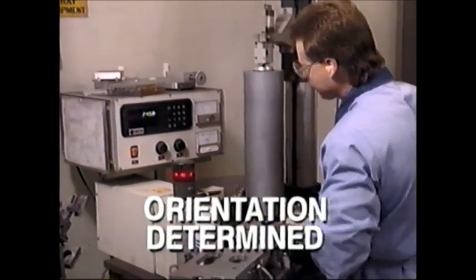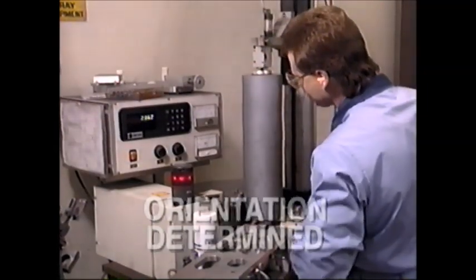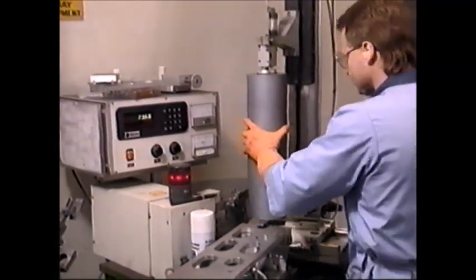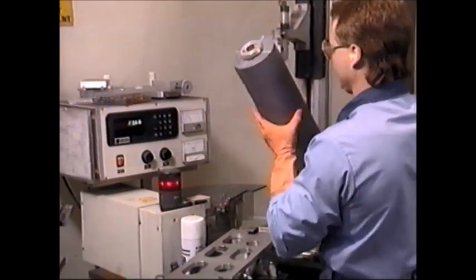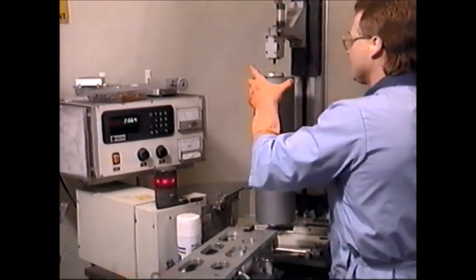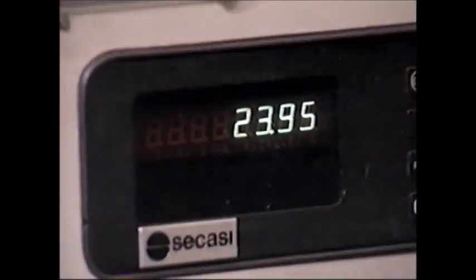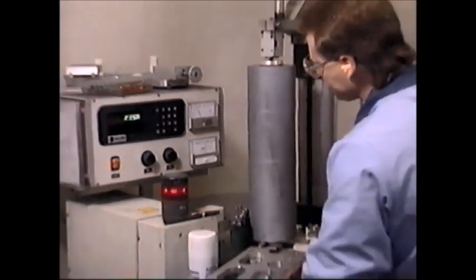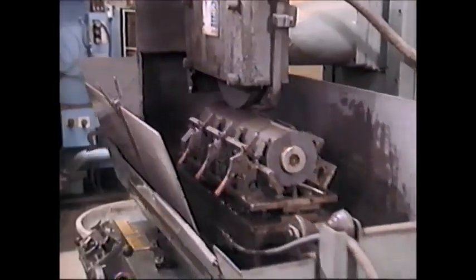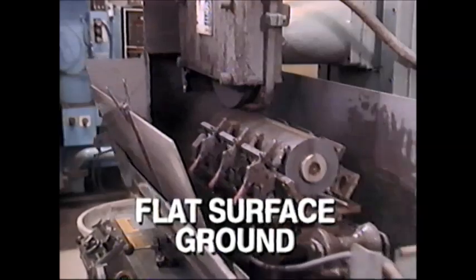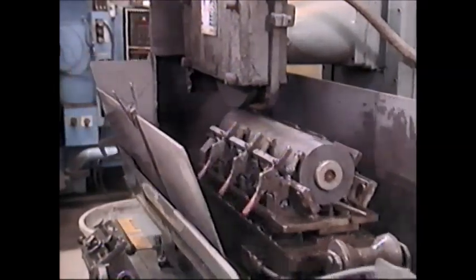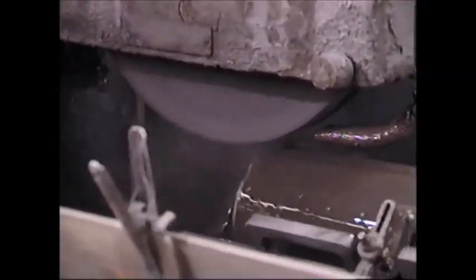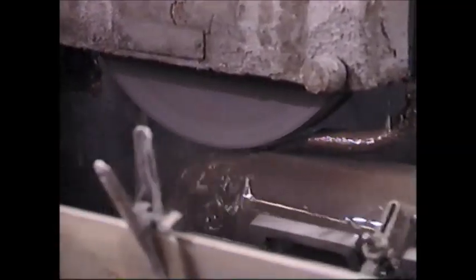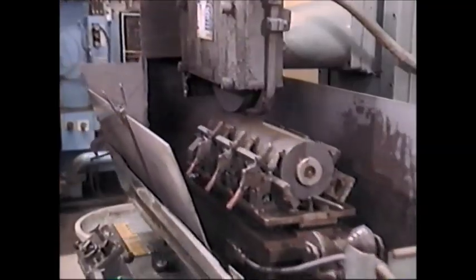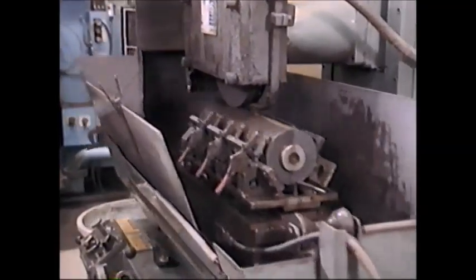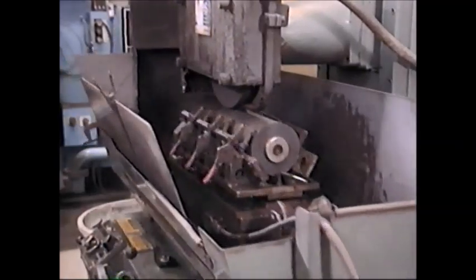The orientation of the crystal planes is very important for the many subsequent manufacturing steps. To check crystal alignment, the ingot is placed in an X-ray diffraction device that produces readings that determine its crystal orientation. Once orientation is determined, a flat surface is ground along the length of the ingot. This flat area provides a key to the crystal characteristics for processes further down the line. It also permits easier alignment for handling during wafer fabrication.